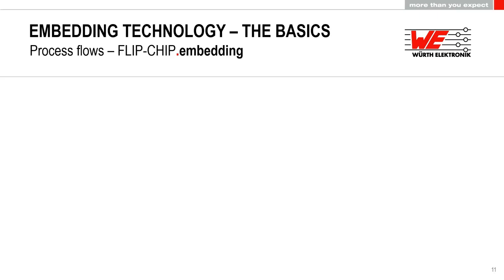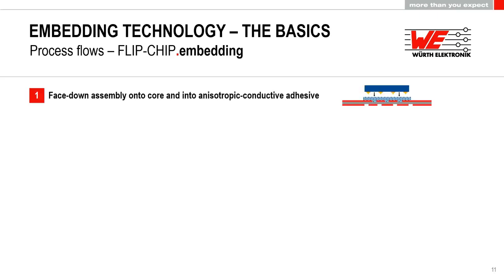So let's move on to the flip chip embedding. Well, basically, we use a pre-structured core here as well. We use the bare die, but we need a bumped bare die in that case. And we use this anisotropic conductive adhesive printed onto the inner layer core. And then we use a thermal compression process and press the component with its pads, with its bumps, onto the pads of the structured core.